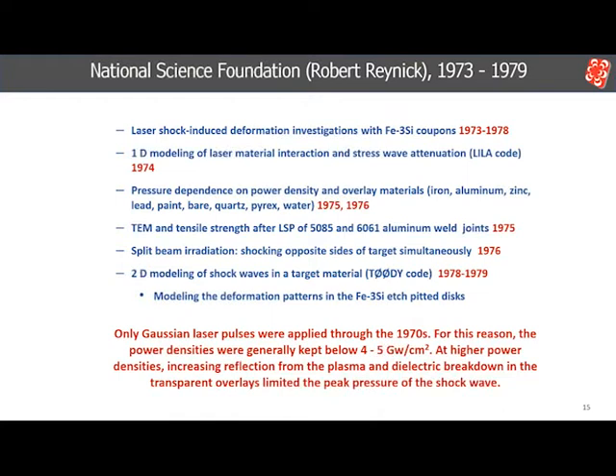The materials effort began with a look at the distribution and intensity of the plastic strain produced by a laser shock wave. Iron-3% silicon alloy was an ideal material to do this, providing direct visual evidence of plastic strain. The physics effort began with an investigation of the pressure dependence on power density using various overlays and of the decay of the shock wave. In addition, computation of the shock waves was begun.